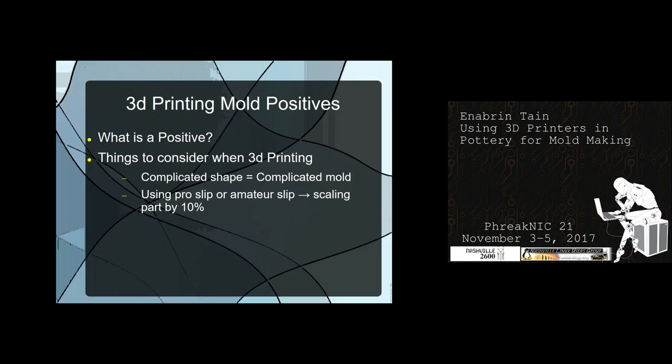You can see on this one there are actually three parts. Another thing to think about when 3D printing a mold is that ceramic shrinks when you fire it, and depending on how you mix your slip, ceramic also shrinks in the mold as it dries. That's a pretty significant shrinkage — that can is actually slightly larger than a regular soda can, which I designed on purpose because I wanted to fit ice and a shot of Jack in it.